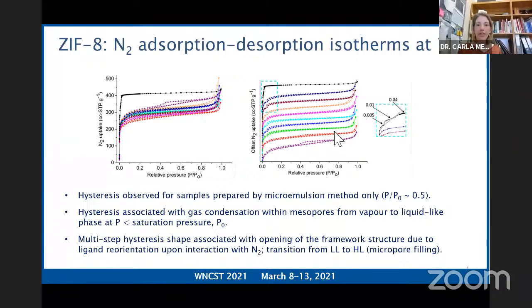And what you can see here is that in all cases, the nanocrystals prepared using microemulsion-based techniques show hysteresis. And hysteresis is known to be associated with the formation of mesopores. And in fact, I didn't include the image, apologies, but we actually are able to see with SEM the presence of the mesopores in these ZIF-8 crystals. So we're going to explore these a wee bit further, but we can clearly see, regardless of the synthetic conditions, in this case using the microemulsion method, we can tune or change the synthetic conditions, but it doesn't matter how we tune them, we always get ZIF-8 and we always get the formation of mesopores. And that always differs from bulk ZIF-8.